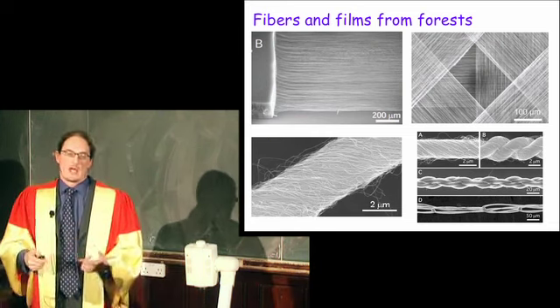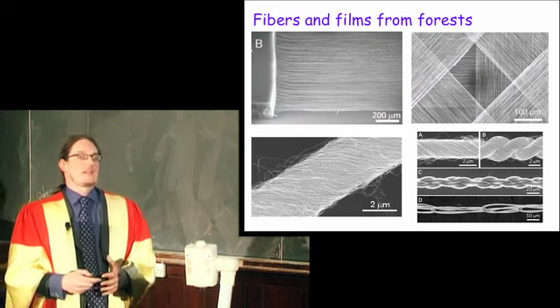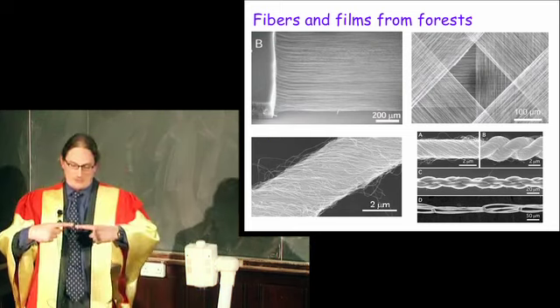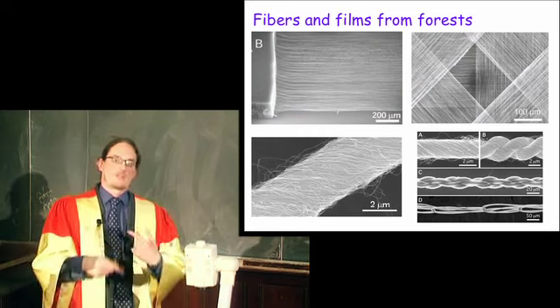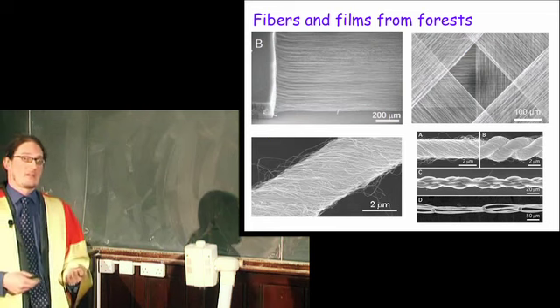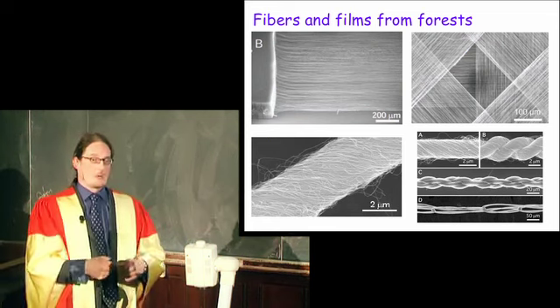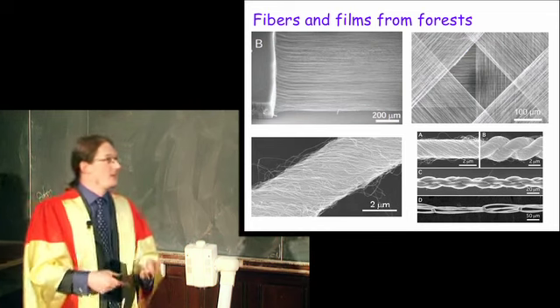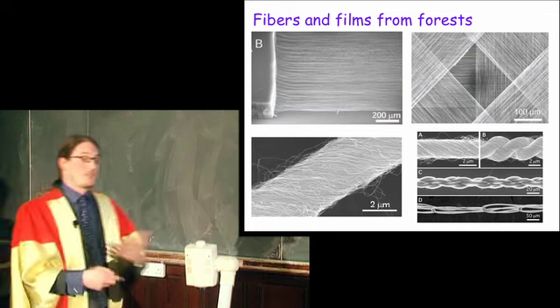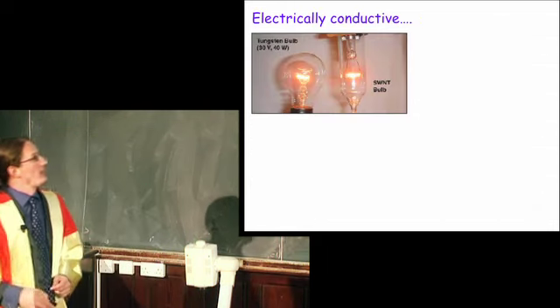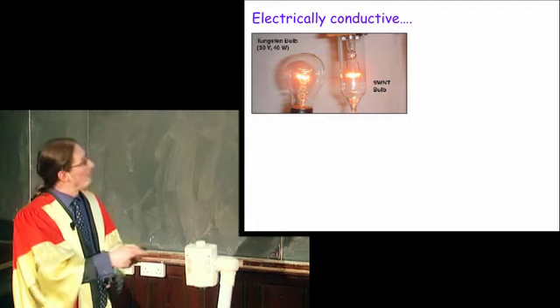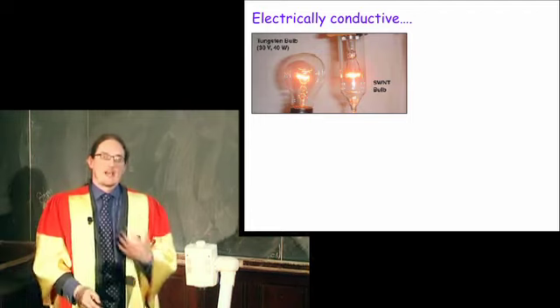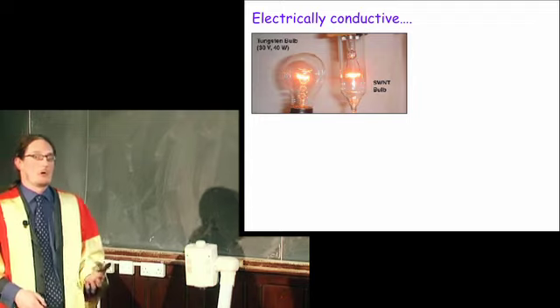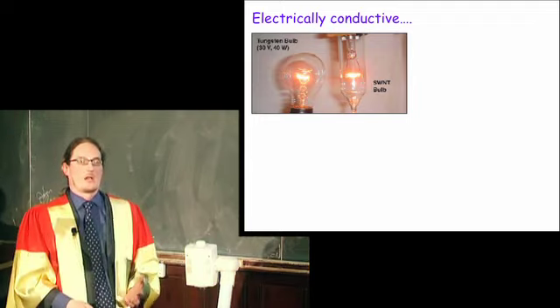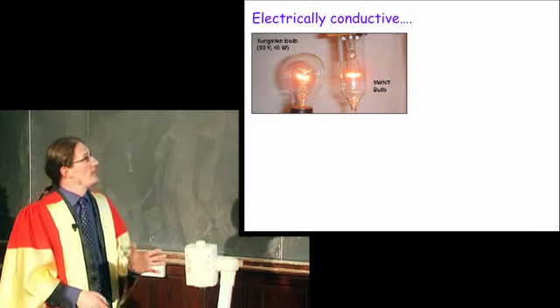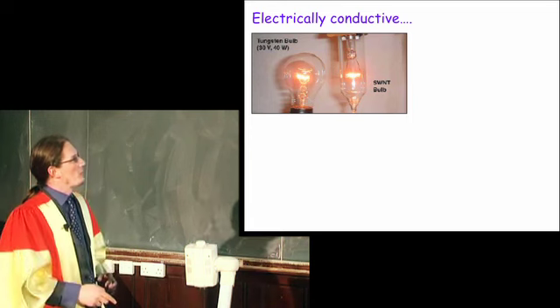Now, that mightn't sound interesting, but previously virtually no one-dimensional nano objects were strong enough to be knotted. And in fact, there's a test called the overhand knot test: if you tie a knot in a fiber and you break it, and it breaks at the knot, then this is just a test for strength in textile science. Now, these fibers, people have put them into light bulbs, and by using accelerated testing, they've shown that a carbon nanotube light bulb lasts 50,000 times as long as a tungsten light bulb. I mean, that really goes to show how different these materials are from normal stuff.